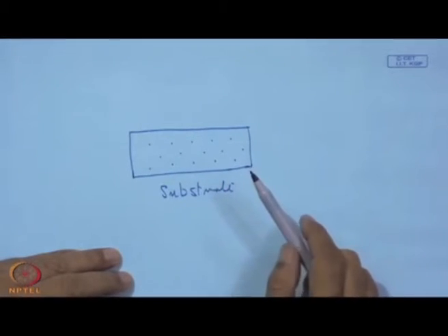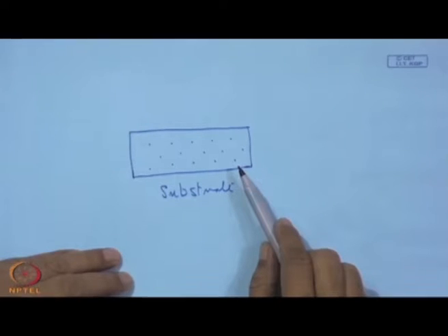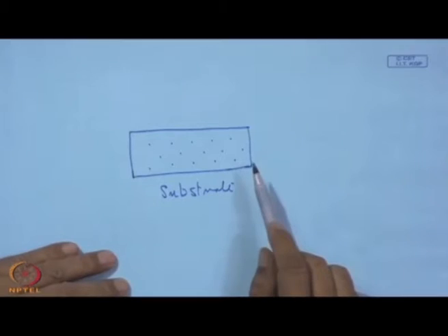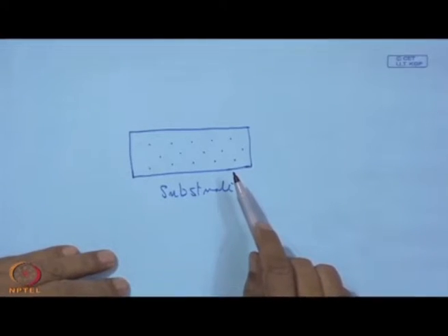So, these are the areas where diamond growth or nucleation happens, that means first of all adsorption of the reactive species, then dwelling or residing on that place, then reaction, that is the third step, and then we have nucleation of diamond, which is going to nucleate and then grow in volume.